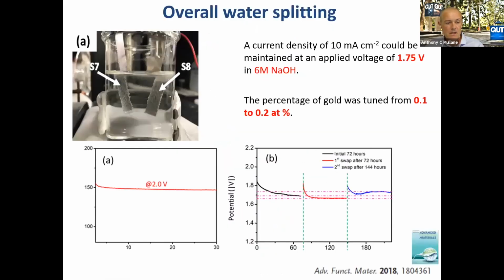And that bodes well for the type of experiment we want to do next. With our 2 electrode setup, we can generate quite good current over a relatively good time period. But then what we did was to mimic turning on and off our electrolyzer - we ran it for a good 72 hours under normal conditions, and then we reversed the polarity, so the anode became the cathode and the cathode became the anode, and we don't see any degradation in performance. We switched it again after another 72-hour period, and again the performance stays the same. So we're excited that the anode and cathode perform at the same level, even if you reverse the polarity of your electrolyzer.